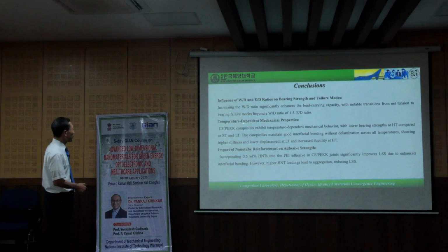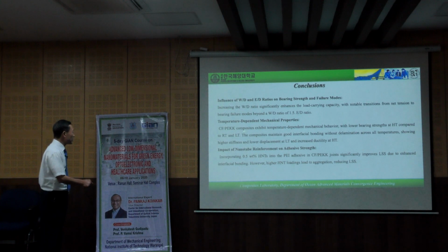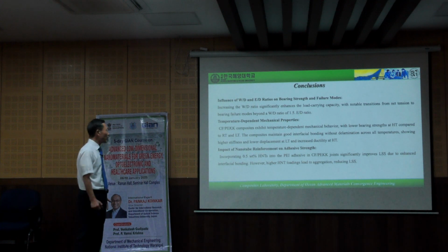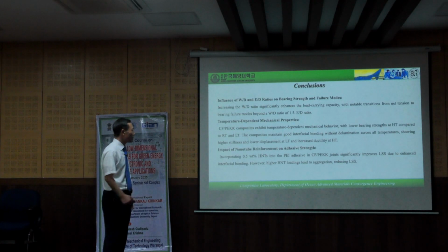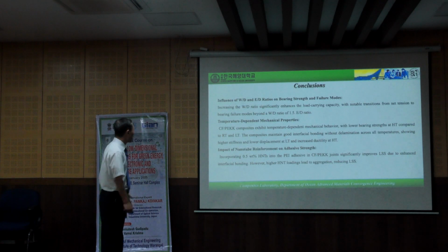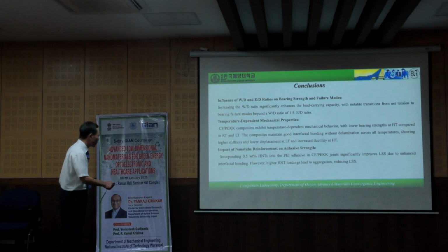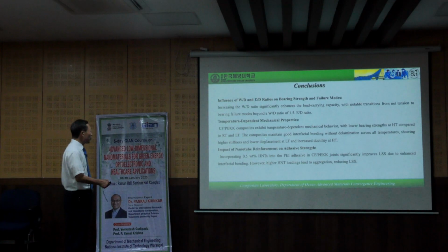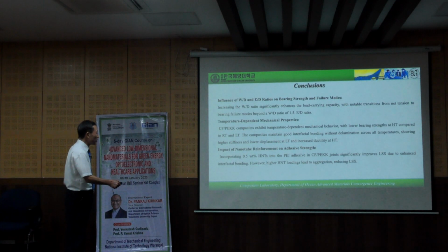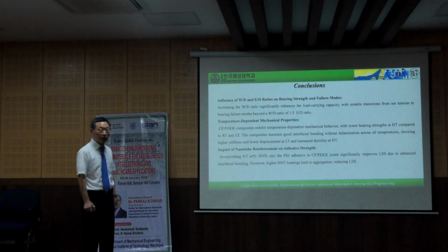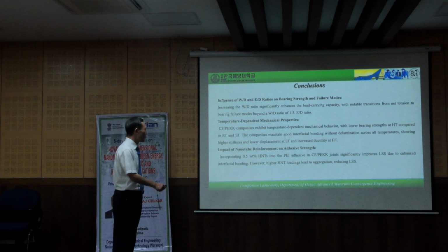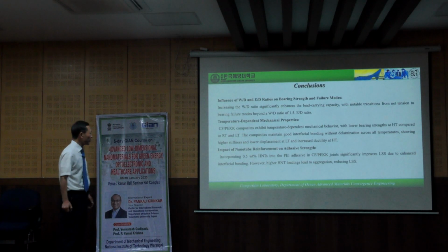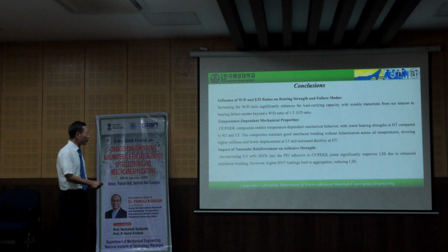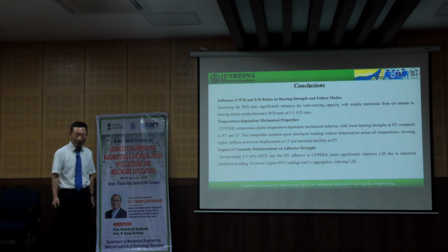And the second, temperature-dependent mechanical properties. CF-PEEK composites exhibit temperature-dependent mechanical behavior with lower bearing strength at high temperature compared to the room temperature and low temperature. The composites maintain good interfacial bonding without delamination across all temperatures, showing higher stiffness and lower displacement at low temperature and increased ductility at high temperature. This is the second result.